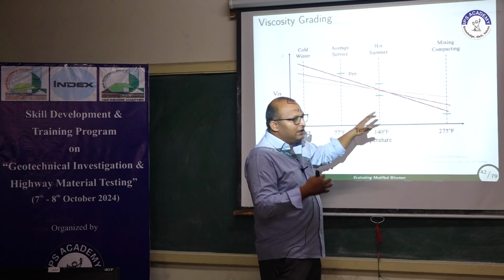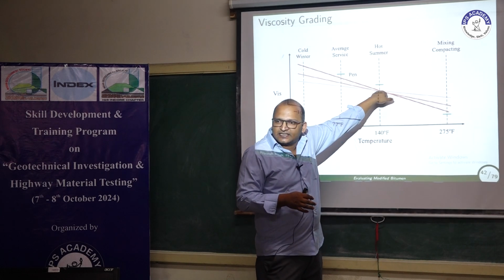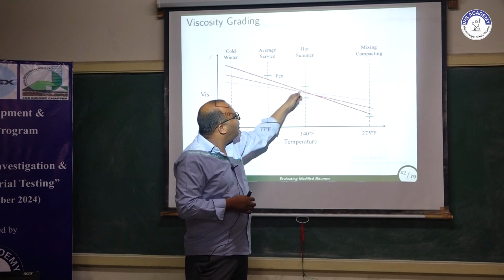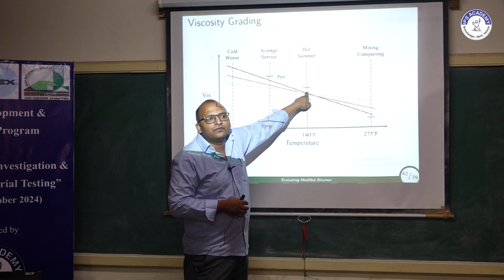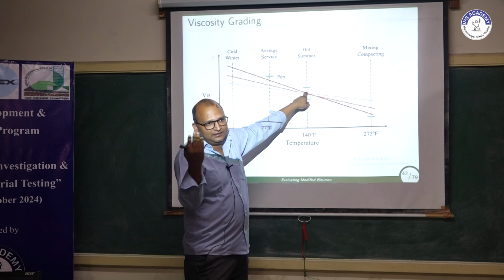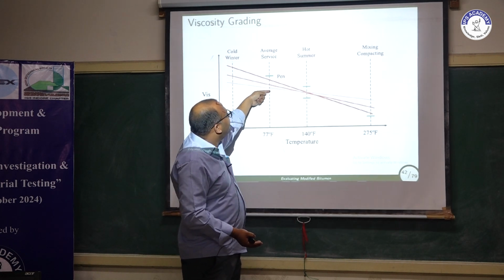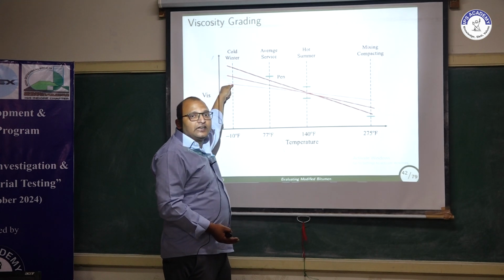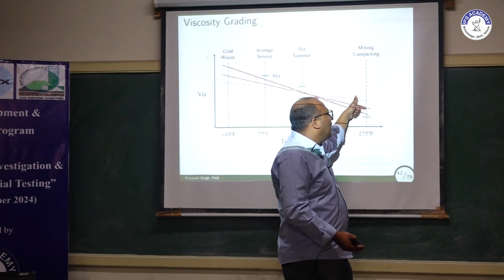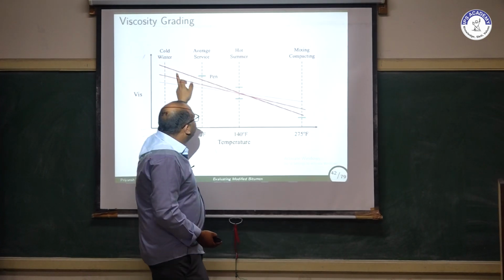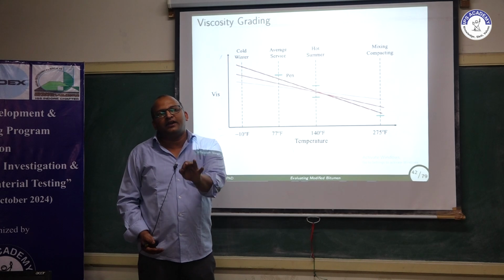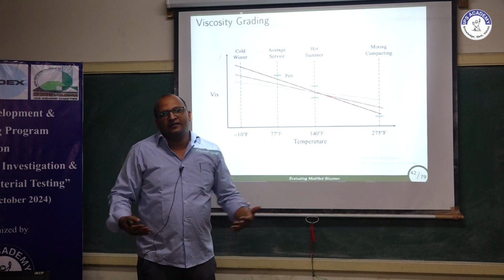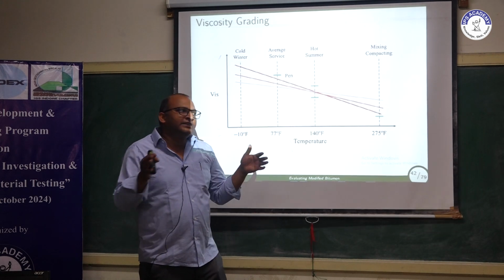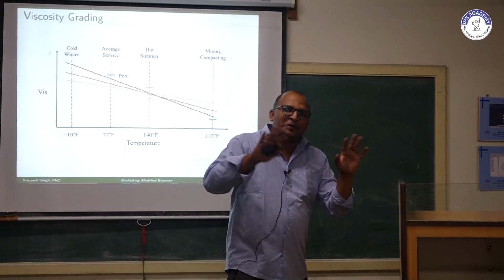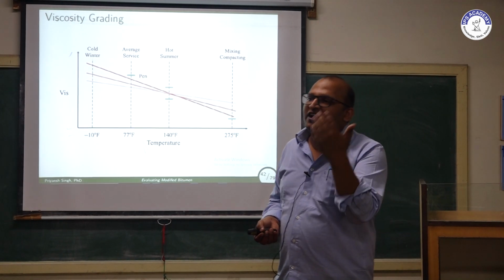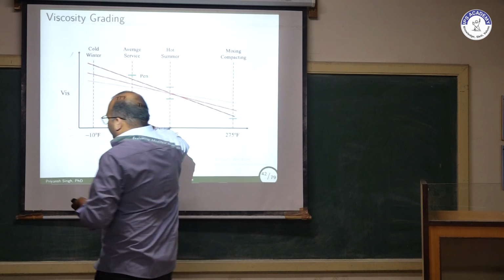Now we are grading our binder based on the viscosity at 60 degrees Celsius. So here if you can see, all these lines have the same viscosity at 60 degrees Celsius. However, their penetration values are different, their performance at cold temperature is different, and their performance at high temperature is different. So should I grade all these binders as the same VG grade binder, or should I come up with a different grading criteria? This is the biggest question that our pavement material people are dealing with: how to modify this grading system in order to account for these problems.